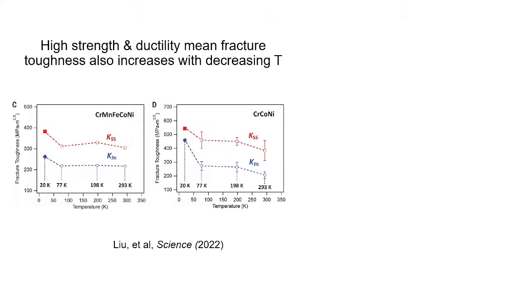And of course, when strength and ductility increase at the same time, then the fracture toughness you would expect to also increase, and that's what you find. Both the steady state fracture toughness and the crack initiation fracture toughness both increase down to liquid hydrogen temperature, right? So you can get very, very high strengths and toughnesses at liquid hydrogen temperatures.